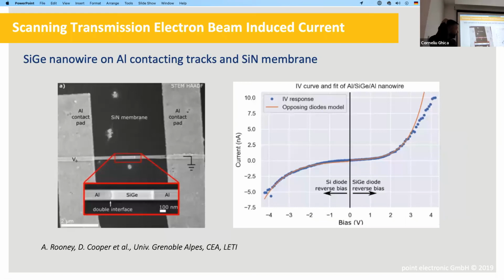Now this is an example of a new, unknown device. This is a silicon germanium nanowire sitting on a silicon nitride membrane, which has been prepared with 2 aluminum contact pads. And it's been through a heating treatment, and aluminum has diffused from the contact pads into the silicon germanium nanowire.